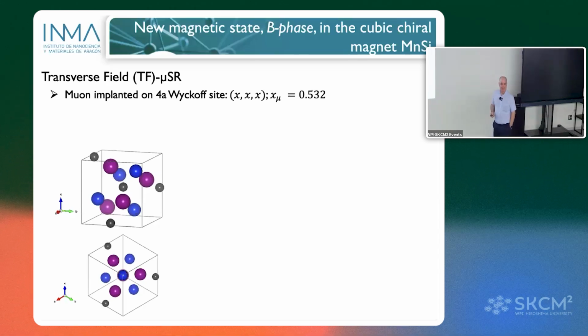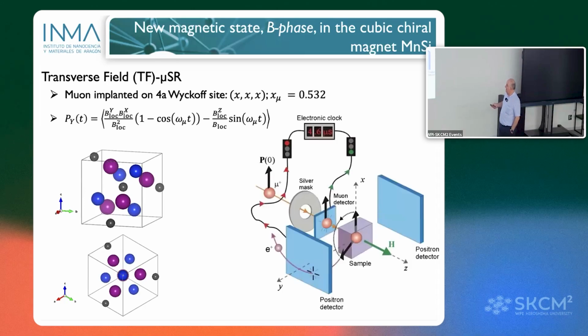Then in manganese silicide, now we need to think in atomic structure. The muon will be implanted in the 4a Wyckoff position, x, x, x. That means along the main diagonals. Here, black points are the points where the muon will be implanted. Well, this is the view if you look along 111. There is one here and the others are there. Then, in this configuration, for example, with these two detectors, applying magnetic field along here, along Z, the crystal axis 111 is parallel to this H, to Z.